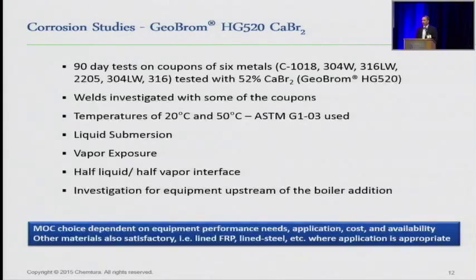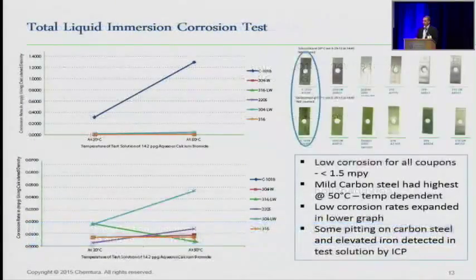or if you have any concerns with your equipment at that point. And basically, for the most part, when you look at the studies, the total liquid immersion, when you see that big blue line, that's carbon steel, and that's still less than 1.5 mils per year of a corrosion rate. Again, it depends on what your application for that metal is, but for the most part, 2 mils per year for most equipment is not a bad thing when you're looking at corrosion rates. It just depends on what you're using it for. But when you take that lower level where the stainless steel and the duplex alloy, and you break it out, that's the bottom graph there, you can see very, very low corrosion rates, and they did very well even in a total liquid immersion environment.